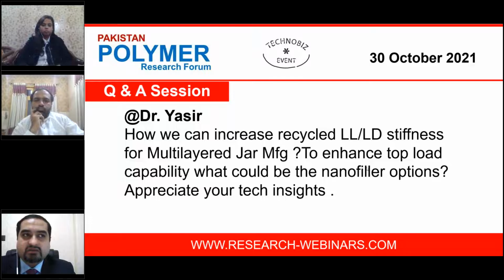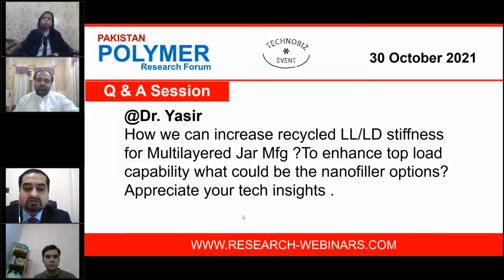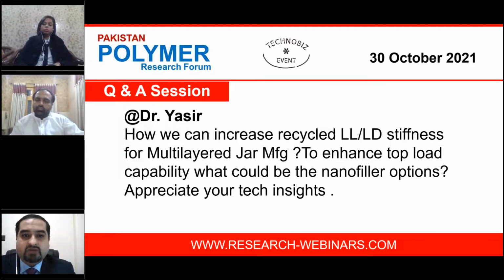Now, there are various ways in which you can surface modify your nanofillers, but there is a precaution that you need to also follow. If the method of modification that you adopt alters the overall food acceptability of your nanofiller, then you will face quite a lot of huge challenges. So what I would normally suggest to the industry in that regard is to try to adopt techniques that are based upon mechanical modification of your filler. For example, you can use ultrasonication, you can use microwave exposure of your filler, as a result of which you can ensure good dispersion and distribution, about which I talked about in detail, and you can get good mechanical properties. I hope I have answered the question.